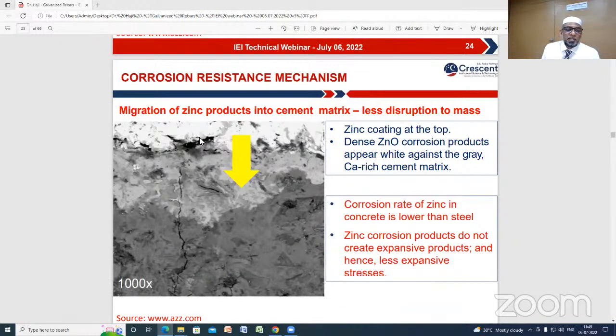Here you are seeing the interfacial transition zone between galvanized rebar and concrete. One advantage in galvanized rebars, as I have mentioned in the previous slide, is that when the corrosion conditions are critical, zinc corrodes and protects the steel. What is the difference between steel corrosion and zinc corrosion? When steel corrodes, the volume increases at a higher rate, and moreover, the size of the particle is larger.